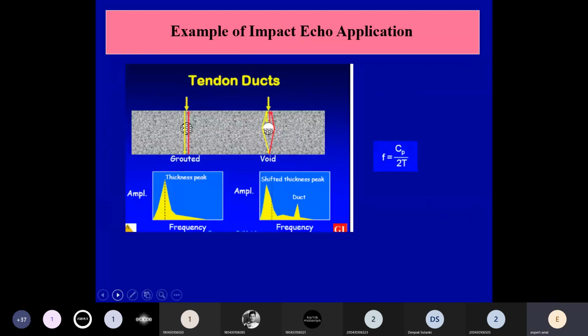An example of this impact echo, I am giving one example here, is a tendon duct. If your tendon duct is properly grouted, the wave will pass through and come back. So your delta T will be as expected. But if you have some voids, it will not pass through the void, it will pass around it. So you will have a shifted thickness peak. It indicates there is some problem in your tendon duct. That means grouting is not proper. There is a possibility of void.